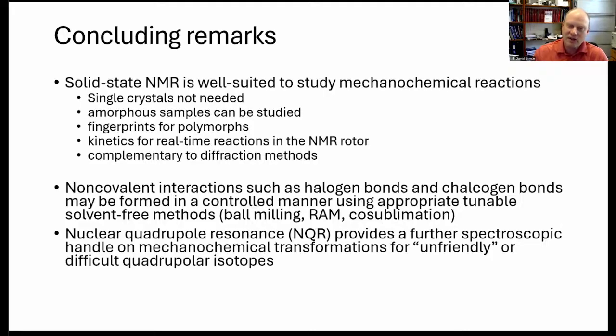So again, single crystals are not needed. We can look at amorphous samples. You get really distinct fingerprints for different polymorphs, just like with powder X-ray. We can look at kinetics for real-time reactions in the NMR rotor. And obviously this is complementary to diffraction methods.